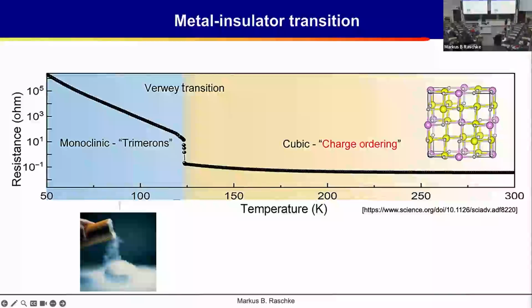So here we are at room temperature, 300 Kelvin. And you're cooling down to about 120 Kelvin. This is just above liquid nitrogen temperature. And then you see a jump in the resistance. So this means that you turn from a metallic behavior into an insulating behavior. This is a logarithmic scale, so you get a first order transition where the resistance abruptly increases by 2 orders of magnitude. Such a phase transition is what you know from water freezing to ice or ice melting back to water. This is similar, a phase transition between a solid and a liquid phase, and here it is between a conducting metallic phase and the insulating phase.